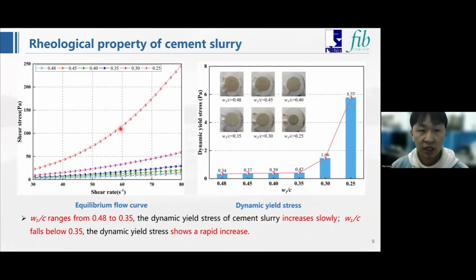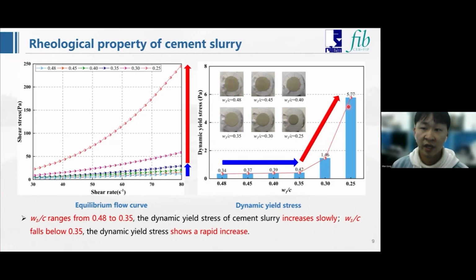We focus our attention on the rheological properties of the cement slurry, as the picture shows. The dynamic yield stress of the cement slurry exhibits two distinct stages. When the water-cement ratio ranges from 0.48 to 0.35, the dynamic yield stress of cement slurry increases slowly. And when the water-cement ratio falls below 0.35, the dynamic yield stress shows a rapid increase. This means the flowability of the cement slurry will significantly decrease.